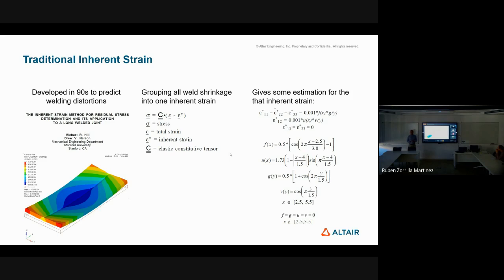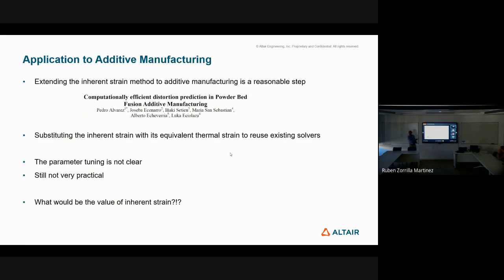The trick is that they are assuming that this was hot, like here, and the entire shrinkage applied directly to it. They calculate the shrinkage that they have until they arrive at the ambient temperature, and then they apply it in a way to that. This is basically the main idea.